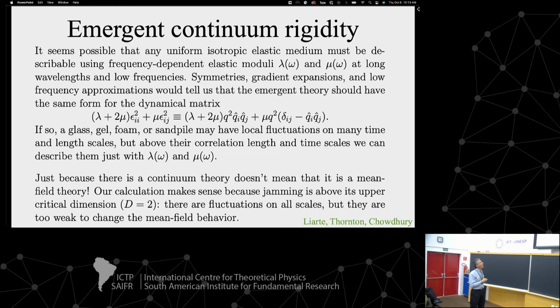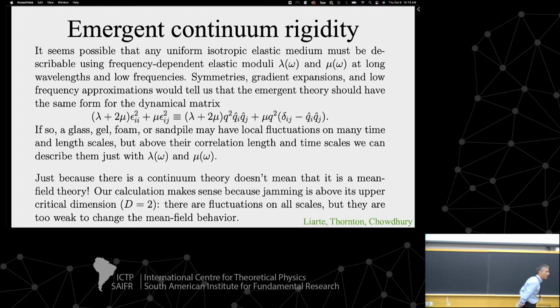So that would mean if you have a frequency-dependent modulus and you stick it into the dynamical matrix like this, that could describe glasses, gels, foams, and sand piles, which on short length scales and high frequencies do very complicated things. But the fact that you don't see those complicated things on long wavelengths, the fact that it seems to be flowing to the universal fixed point of homogeneous isotropic elastic, which is not trivial but appears to be true, maybe we can just calculate these two constants. And our job as physicists is to do these two or something equivalent. That would be an immense simplification in some ways.